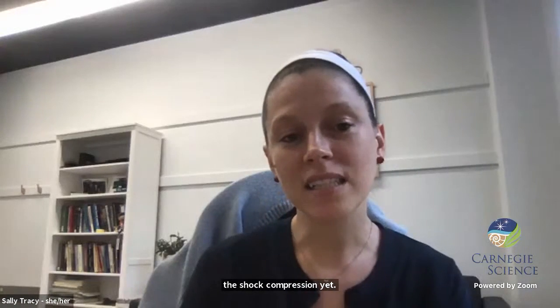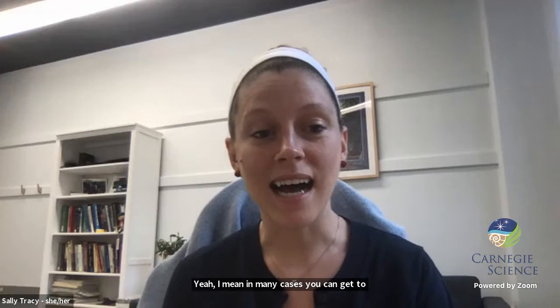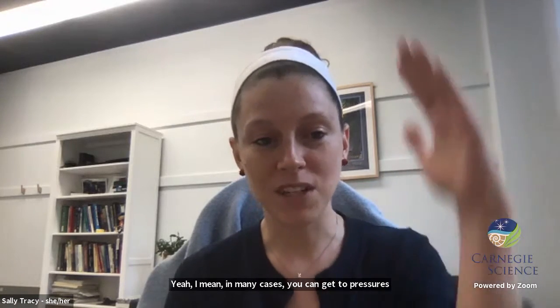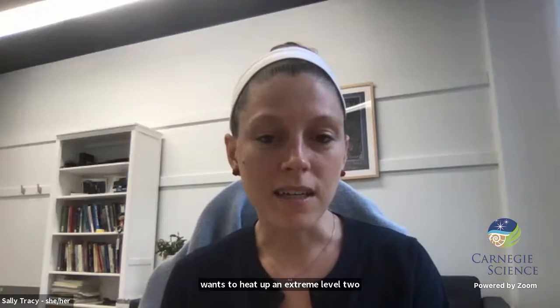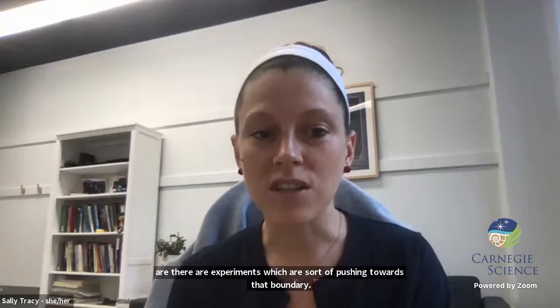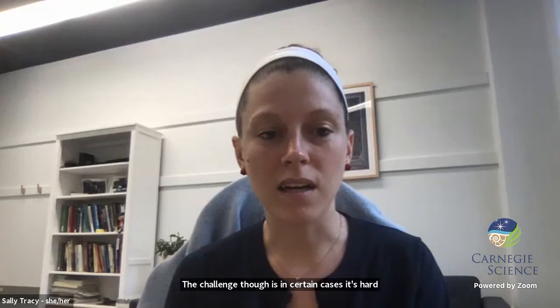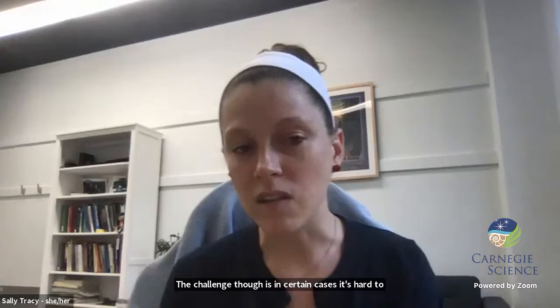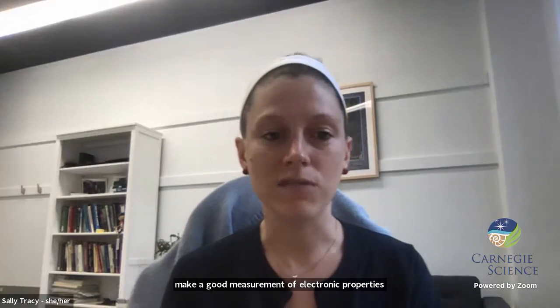Yeah, in many cases, you can get to pressures that high. It's challenging to keep the temperature low enough in certain cases, because when you get to very high pressures, everything wants to heat up to an extreme level too. However, there are experiments which are pushing towards that boundary. The challenge, though, is that in certain cases, it's hard to make a good measurement of electronic properties at those conditions.